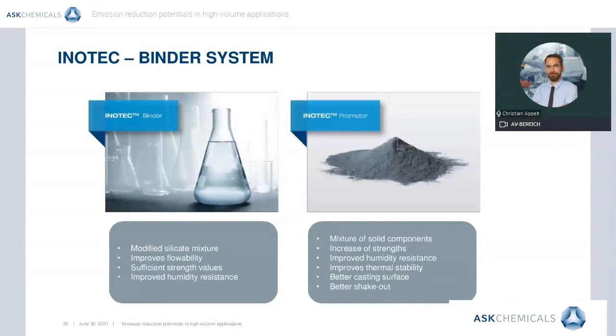Component 2 is the powdered Inotec promoter, which is a mixture of synthetic and natural raw materials based on a completely inorganic product composition. Through the use of the Inotec promoter, primarily mechanical and thermophysical parameters during the core production process, but in particular during the casting process, can be adjusted to assure castings of high dimensional accuracy and high surface quality. The main function of this component is to increase immediate core strength for fast ejection in the core production process.